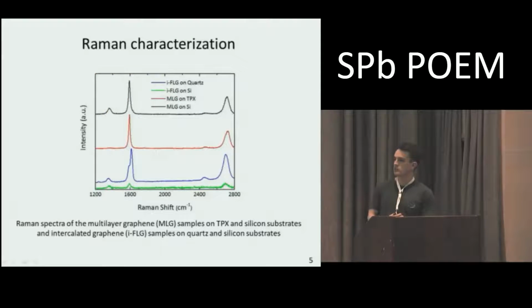In our experiments, we investigated 4 samples. They were multi-layered graphene on dielectric and semiconductor substrate, and few-layer graphene intercalated with ferric chloride, also on dielectric and semiconductor substrate. Here you can see the Raman spectra, which are provided for quality evaluation of the samples, and it's seen that multi-layered graphene has low defectiveness, but after chemical modification, samples become more defective.